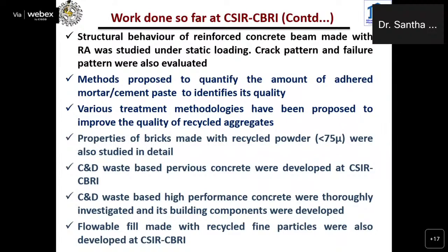Generally, whenever we make recycled aggregates, more than 10 to 20% is a byproduct that comes from the recycled aggregate. That material, which is less than 75 micron, we have used for making bricks. And also we have used C&D waste. We have developed various products like C&D waste based pervious concrete, self-compacting concrete, and permeable pavement. Just go to the next slide.